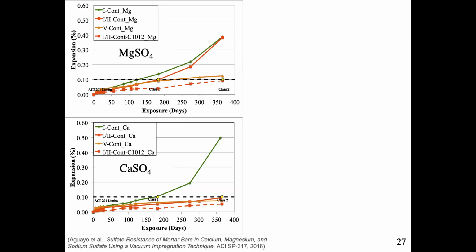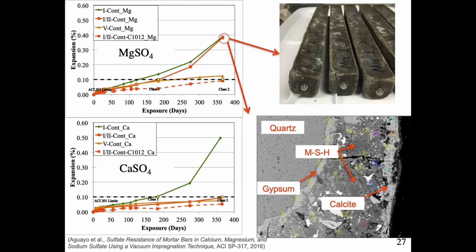So yeah, that's pretty much what we've done at this point. We also have a publication looking at other types of sulfates. This is calcium, magnesium. You see similar performance, right? This is the control with the solid line. This is the vacuum impregnation, the dashed line. So again, in all cases with the type 1 to type 5, much faster acceleration of expansion. Same thing with the calcium sulfate in this case.